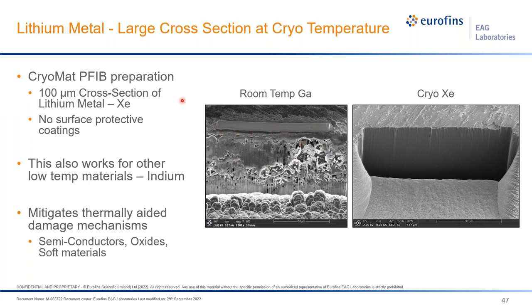So now, what if we combine P-FIB plus also having cryo capabilities? In this case, we've got a cryostat in the P-FIB itself, which is going to allow us to operate in cross-section, I think down to about -140 to -160°C. So this works great for other low temperature materials like indium as well.